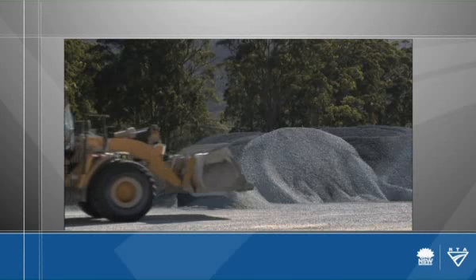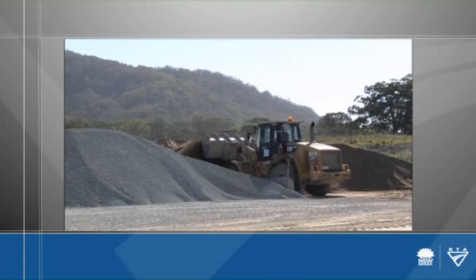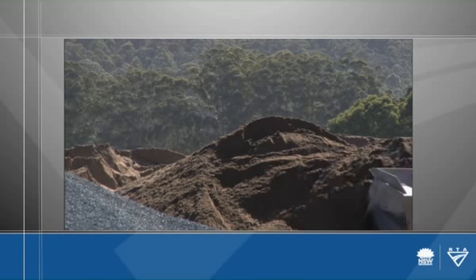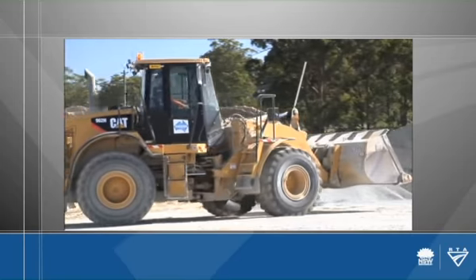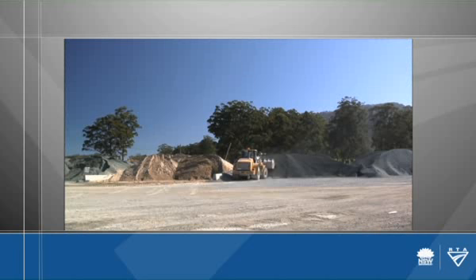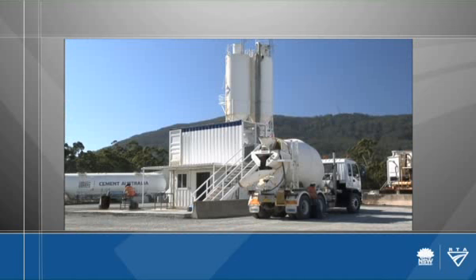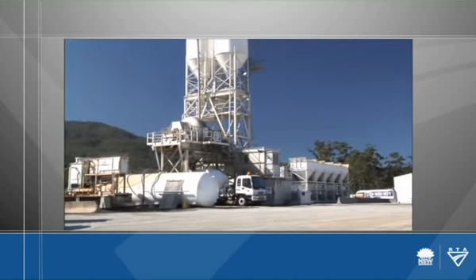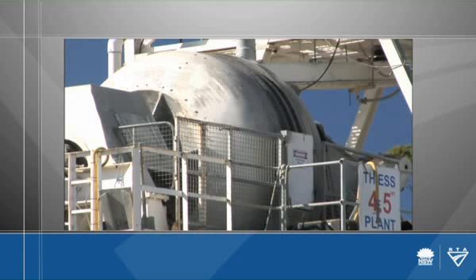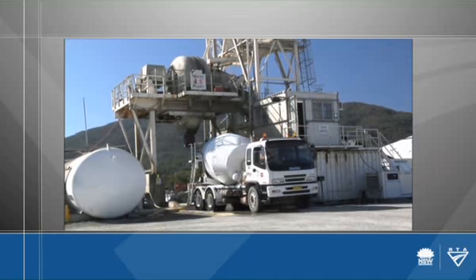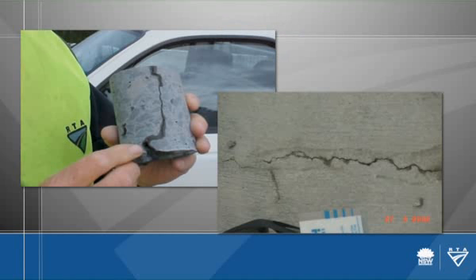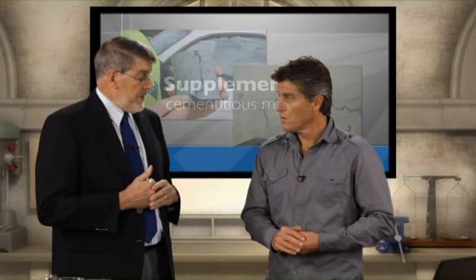Yes, Peter, and one in particular that's worth mentioning, I think, is manufactured sands. Because of the lack of availability of some fine aggregates, crushed rock is now being used as a fine aggregate. The only problem with that material is that it has the potential to absorb moisture. So what happens is the concrete can be batched, be on site, and then absorption will occur. The water will be taken up into the fine aggregate. The concrete will lose workability and become very difficult to compact. And what it led to, in some instances, was very severe cracking of a deck, where the deck had to be removed because of the problem. So the manufactured sands have to be controlled, but the specification now requires that the absorption of the fine aggregate can only be 2.5% of the water.